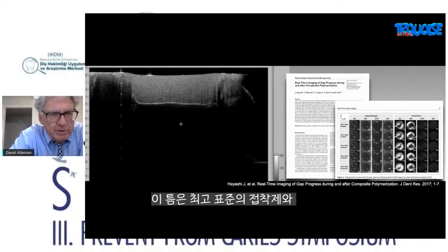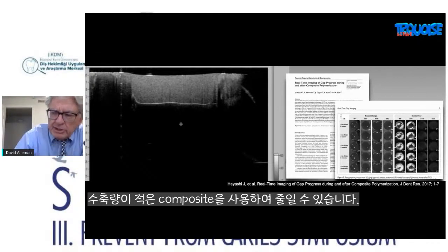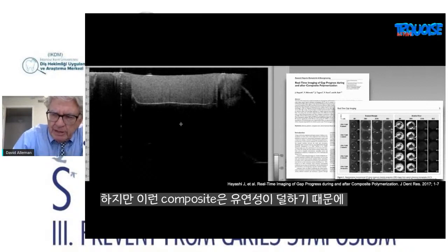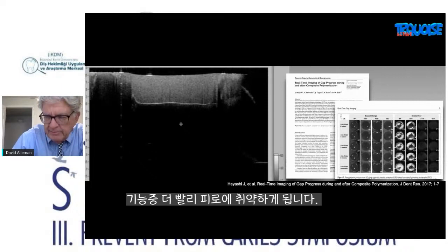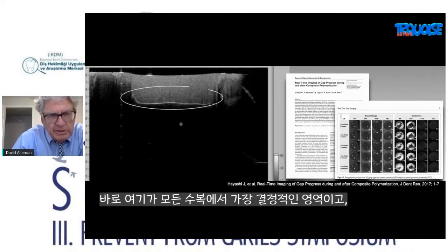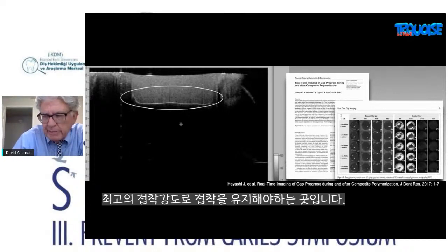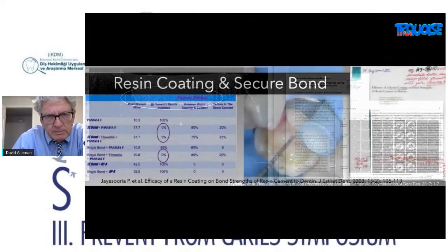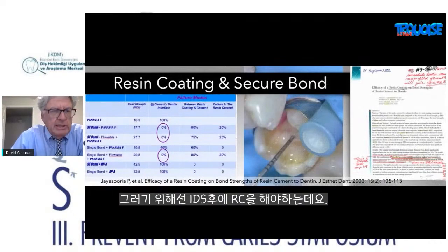Now that gap can be reduced by using a gold standard bonding system and using a composite that shrinks less. But composites that shrink less are usually more flexible, and then under function, they become susceptible to faster fatigue also. So this is the critical area in every restoration, and this is where we need to stay bonded at our highest bond strength. So the way to do that is with a resin coating after the immediate dentin sealing.